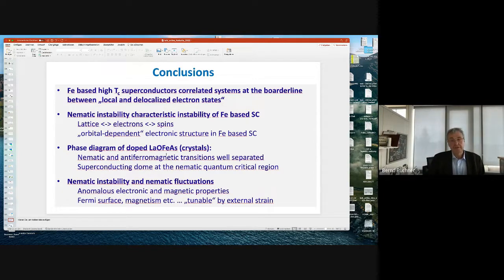I've presented this phase diagram for the first time with these two well-separated transitions. This is the superconducting dome at the nematic quantum critical region. And then at the end, too fast, I admit, I've argued that this nematic instability leads to a very unusual normal state, a very unusual metallic state. That's also the fact that we're really dealing with a bad metal, and that a lot of these properties are tunable by external strain.